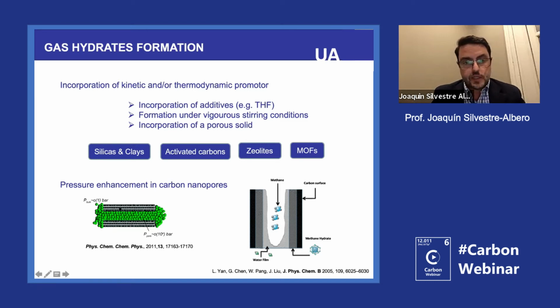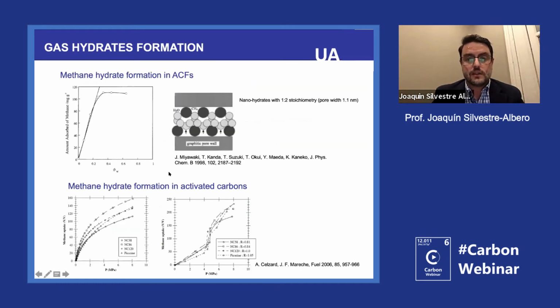So here I put an example of a paper from the group of Professor Gubbins. And this is nice because in this study, they were doing theoretical calculations of how much the pressure can be enhanced in a carbon material. And they were predicting that when you have 1 bar in the environment, inside the cavities, you can even reach 10,000 bar. So this is what we were trying to do. Why can we take advantage of these confinement effects to promote the growing of crystals that need high pressure? And that was, as I said, our main goal in this investigation.